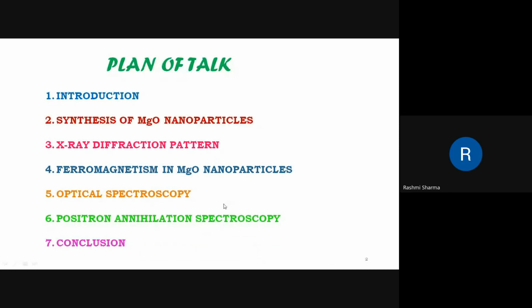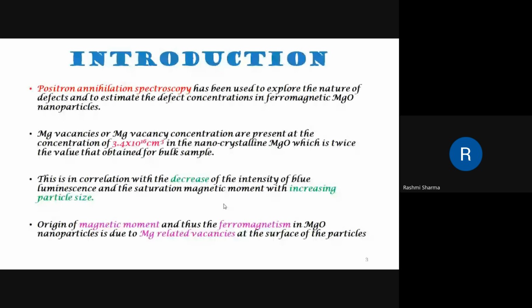Continue. So we will discuss how magnesium oxide nanoparticles are synthesized. And then we discuss the X-ray diffraction pattern, ferromagnetism in magnesium oxide nanoparticles, then optical spectroscopy, positron annihilation spectroscopy, and then we will move on to the conclusion. So here is the introductory part. Basically, there has been a lot of interest in the study of the magnetic behavior of nanoparticles of otherwise non-magnetic materials because they exhibit ferromagnetism at room temperature. So, following these facts, in this paper the authors have shown that nanoparticles of magnesium oxide also exhibit room temperature ferromagnetism. In order to prove this, they have employed a technique called